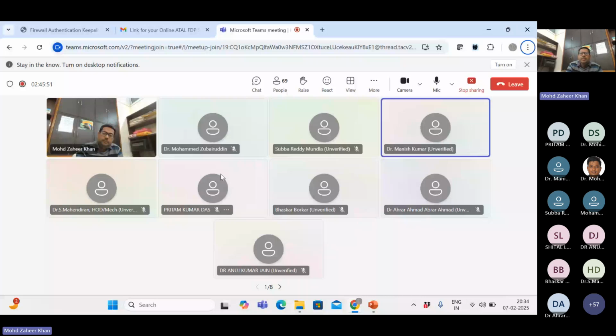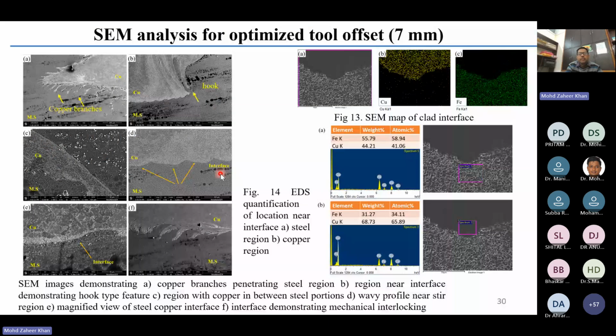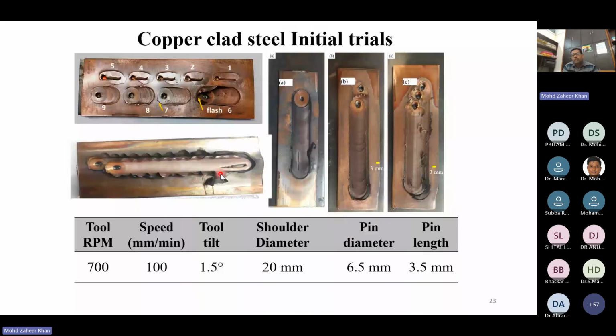So in our case, we did several trial runs, and the process parameters I will give, it is there in the PPT also. So for this cladding operation, we used these parameters. Tool RPM was 700 RPM, tool speed was 100 millimeters per minute, tool tilt was 1.5 degrees, shoulder diameter of the tool that we have chosen was 20 millimeters, the pin diameter was 6.5 millimeters, the pin length was 3.5. The shape of the pin was in the shape of a truncated cone. There were no thread marks or any type of marks that were made on the pin.